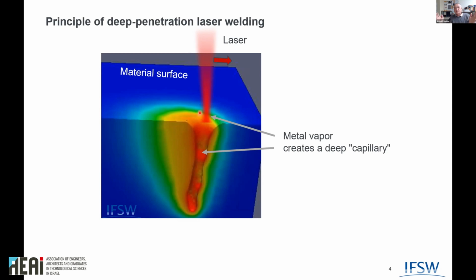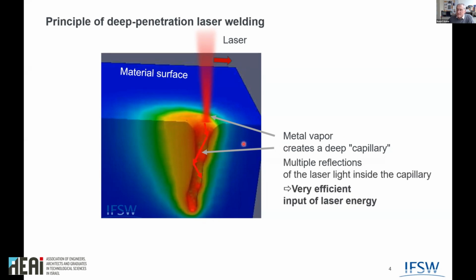The laser heats the system up to boiling temperature. We create vapor, and the vapor pressure presses the melt away, creating a kind of capillary, as it's called. What is important with this capillary is that it's quite deep, and if you look at the laser as rays, you can see that there are multiple reflections inside this capillary, which means that almost all the energy in the laser beam is coupled into the process, which makes the process very efficient and very useful for deep welds.